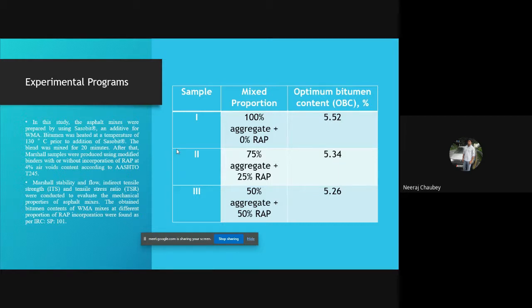The optimum bitumen content was found to be 5.52 for mix 1, 5.34 for mix 2, and 5.26 for mix 3. It can be seen here that as we increase the RAP content, the optimum bitumen content decreases, though it decreases only slightly.